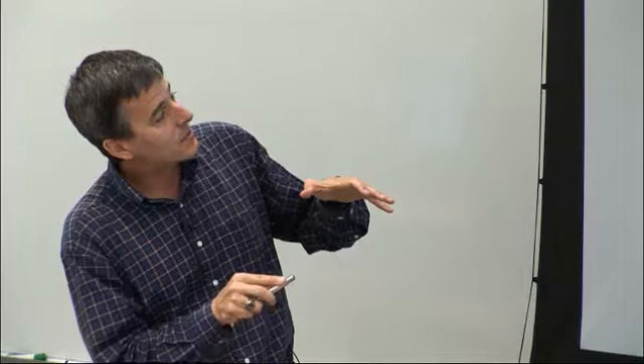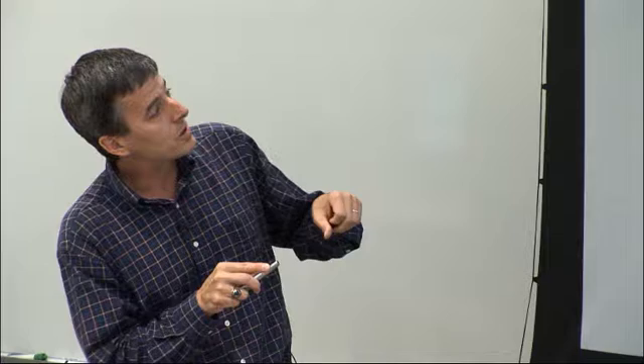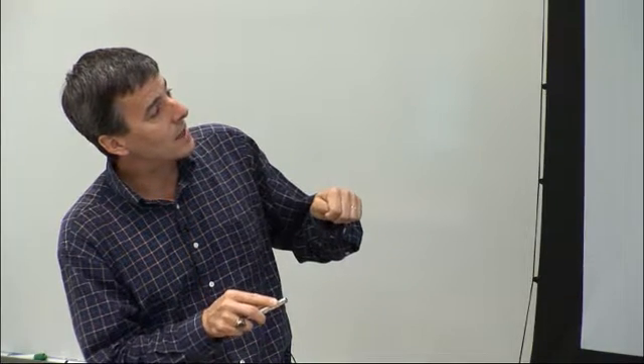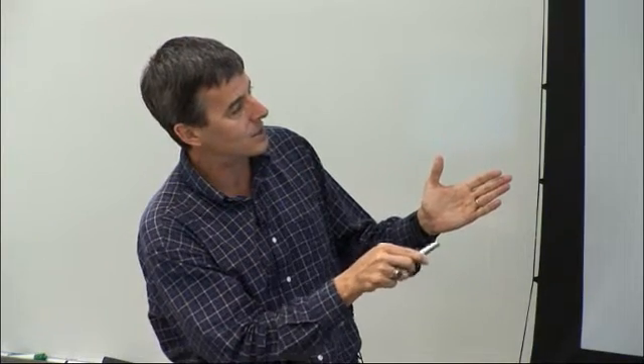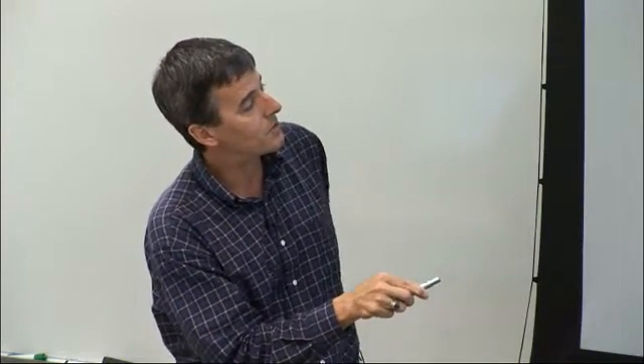So I'm not going to go through all the details. Let me just highlight the key points. So if you think about modeling the mechanics of a piece of electronics, just a generic material bonded to the skin, you can run different scenarios in terms of the modulus of the electronics and its thickness. And you can calculate interface stresses in particular that tend to drive delamination. Those could be shear stresses or peeling stresses, and you can do it for different scenarios. Silicon chip glued to the skin, flexible electronics, so plastic sheet on the skin, thinner, lower in modulus, or all the way to this kind of tattoo-like construct that I put forward in the previous slide.